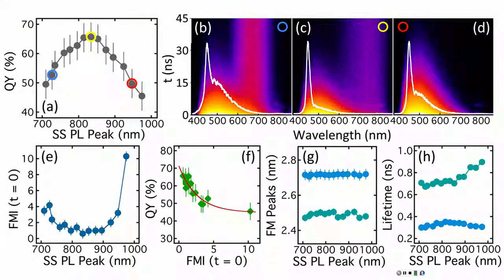Oh, but it's a silicon crystal, right? Silicon nanocrystal, yep. But for quantum dots, they're not applicable, right? Well, there is a hypothesis in the community, which is controversial, that on the border, when it goes from the nanocrystal to bulk, it's still a confined structure, but it has some traces of the band structure. What's the Bohr radius and what's the size of the crystals that you're plotting? 2 to 4 nanometers.